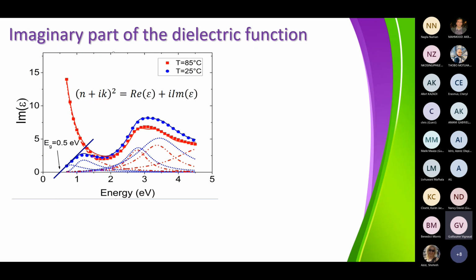The first thing that I want to comment on is the imaginary part of the dielectric function. There is a very well-known relationship between the dielectric function and the index of refraction. Guillaume has shown you that you can get N and K out of ellipsometric measurements. If you take this complex quantity and square it, you get the dielectric function of the film. So this is what we did. Once you have used this relationship, you can extract the imaginary part of the dielectric function, and you can see that it evolves quite differently at room temperature or in the metallic phase.